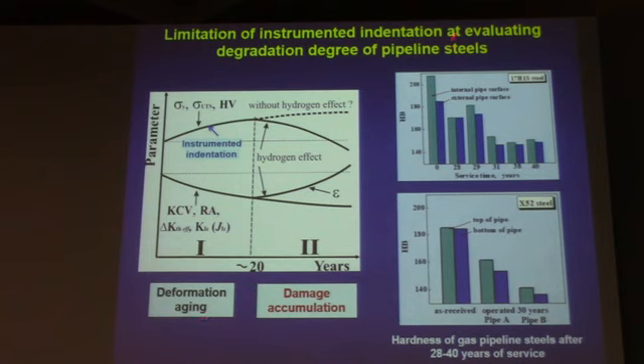And the usage of this method can be limited if degradation degree of a tested metal is high, when the second stage associated with damage accumulation is dominated, because in this stage strength and hardness decrease. So it's proposed to use for evaluation of degradation degree for metal being operated at the second stage with damage accumulation, additionally non-destructive electrochemical method.